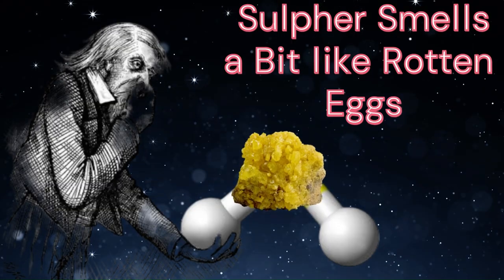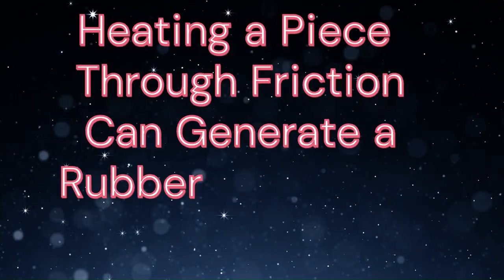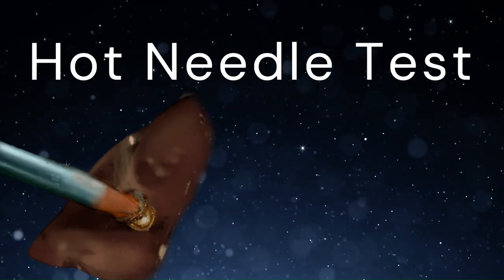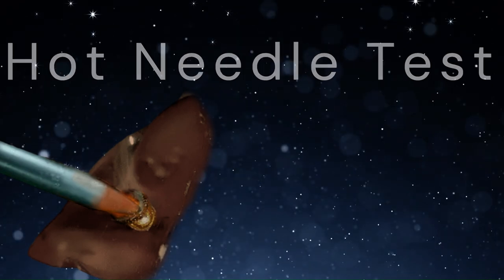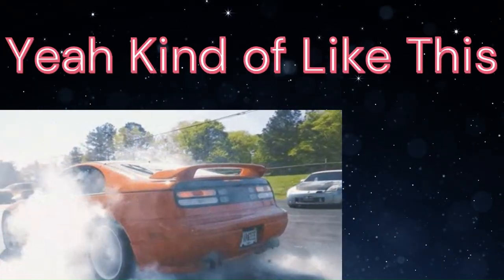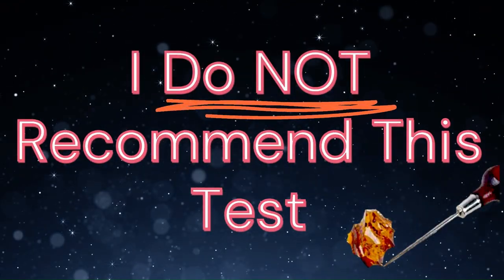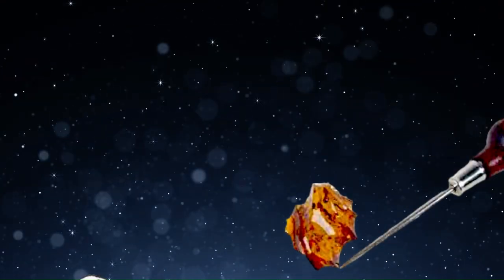The smell test: it'll smell a little bit like rubber or sulfuric. If you're rubbing it and putting heat to it, it's going to have one of those slight smells. You can also do a heated needle test in an inconspicuous area — it'll pretty much just sink right into the vulcanite with hardly any resistance and it's going to smell really rubbery, kind of like a burnt tire smell. I've never liked these hot needle tests — not on bakelite, not on vulcanite — so I don't recommend it, but if you're dying to know, this is one way to tell.